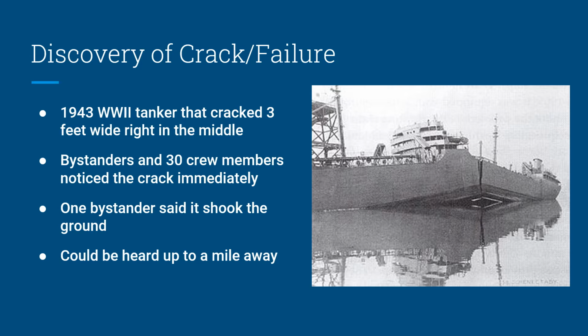So first I'm going to talk a little bit about the discovery of the crack/failure. The SS Schenectady was a 1943 World War II tanker that cracked right down the middle, and this crack was about 3 feet wide. At the scene, there were bystanders and about 30 crew members who noticed the crack immediately. One bystander said that it even shook the ground around them. It was later reported that the crack of the SS Schenectady could be heard up to a mile away.